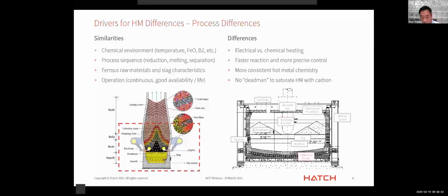In the ESF process, the residence time, as well as the ability to control the process through direct intervention, slag chemistry, or direct control of the furnace power input, allows much faster and precise control of both the heat and mass balance of the process. This has a very positive impact on the consistency and quality of the hot metal we produce at the end. Coupled with the much larger hot heel, even larger than the blast furnace at over 1,000 tons at the bottom of the ESF, this certainly allows much more consistent product quality, which a BOF operator will certainly appreciate. As we know, blast furnace hot metal quality swings can be quite detrimental to a consistent and steady BOF operation.